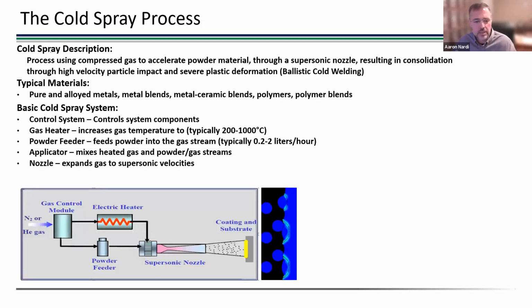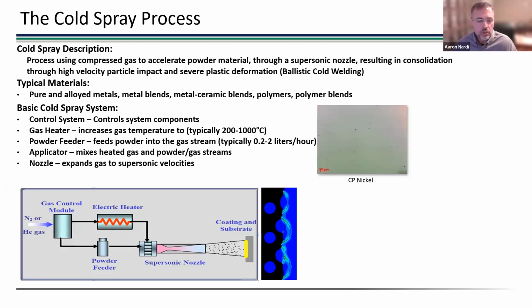So the systems typically consist of some sort of control system, usually a gas heater, because we say cold, but what we mean is less than the melting point of the material. We have to feed the powder somehow, then we have to mix the powder with the gas, and then it goes through the nozzle. When you do it right, you get a nice dense deposit.